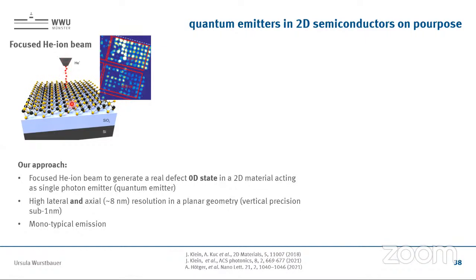Due to this focused beam, which is much less than 1 nanometer, you can get high lateral precision, about something like 8 nanometers, because you generate secondary electrons by this bombardment. However, 8 nanometers is still quite good. And in the Z direction, the precision is the thickness of the material, 0.7 nanometer. So meaning it's really high.